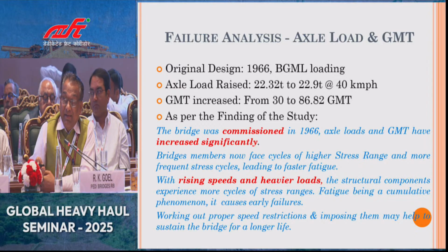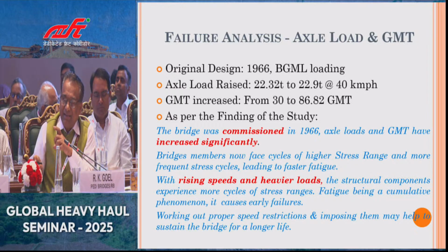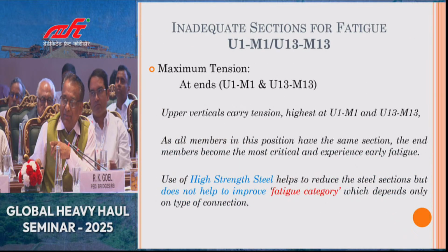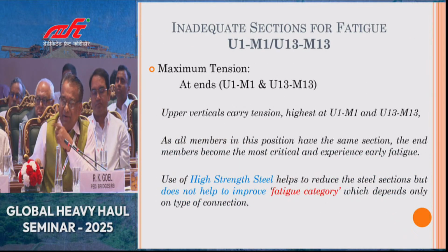So basically, the members were subjected to heavier, rather larger stress ranges as compared to earlier, and more number of cycles because of increased GMT. So that was the prime cause of this failure. Then the vertical, I have told you, it was having the tension, and it was highest in the U1 M1. The same member has failed, which was having the highest tension.